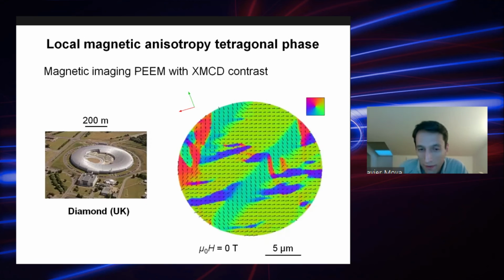If you go further, then you can do actually magnetic imaging. This is similar to the images that I showed you before, but instead of looking at magnitude only, we are going to look at magnitude and direction. This image is of these samples at room temperature. You can see that there are two distinct regions. There are regions like this one here, where the magnetization is either pointing right or left. And then there are regions like this one here, where the magnetization is mostly pointing down or up. And you can see that this pattern repeats. So you have this kind of microstructure, which is unusual for LSMO, because LSMO on its own will not show this microstructure and this local magnetic anisotropy.